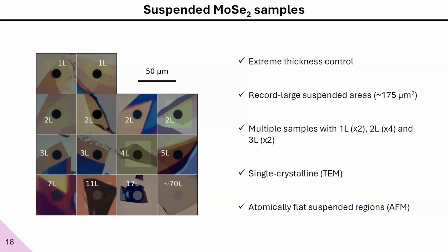We made multiple samples with 1 layer, 2 layers, and 3 layers to study sample-to-sample variations, or the reproducibility of our experimental techniques. We then characterized these flakes, which I will not show in this talk, and we confirmed that they are single crystalline. They come from a single crystalline bulk material, and therefore they preserve high crystallinity. We used AFM on the suspended regions, and this revealed atomically flat suspended regions. This is not the case if you put them on a substrate, because these materials are so thin they will conform to the roughness of the substrate.